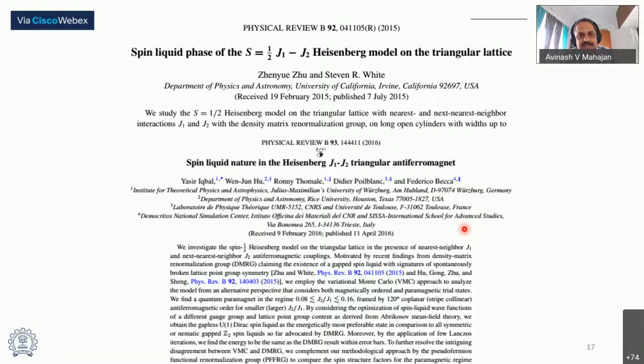The key feature here is that one sees gapless excitation. There's no exponential reduction observed in the susceptibility or the heat capacity, but rather a quadratic variation of the heat capacity. And this arises from Dirac cones, which are present in the band structure of this material.